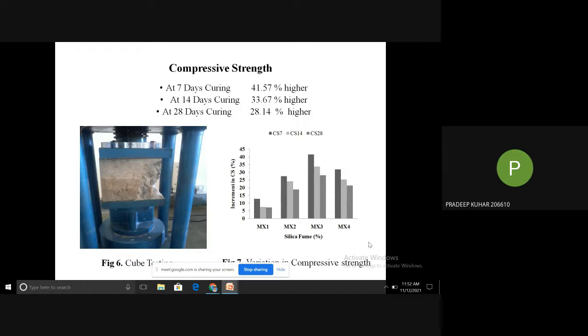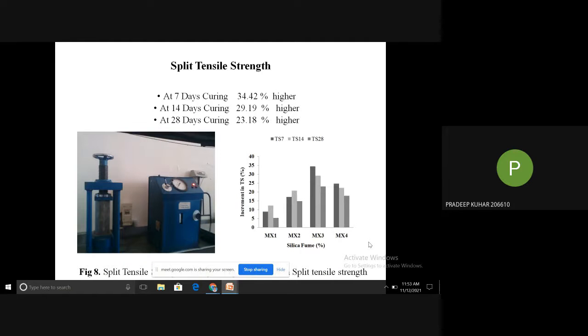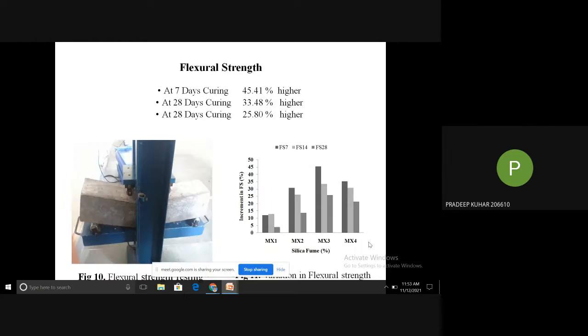So it is evident that with the addition of silica fume, there is enhancement in the early strength of the concrete. Similarly, the split tensile strength also increased by 34.42% at 7 days of curing, about 29.19% after 14 days, and about 23.18% at 28 days higher than that of the normal concrete, that is MX0 specimens.